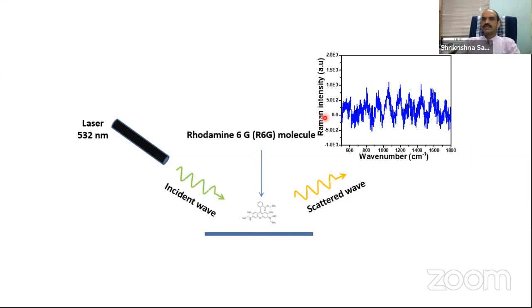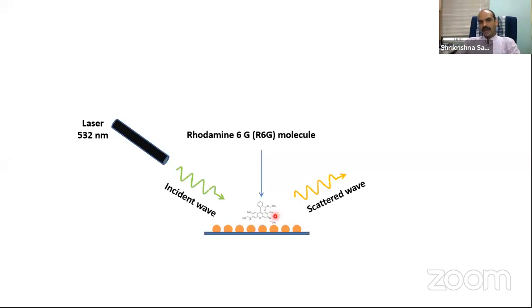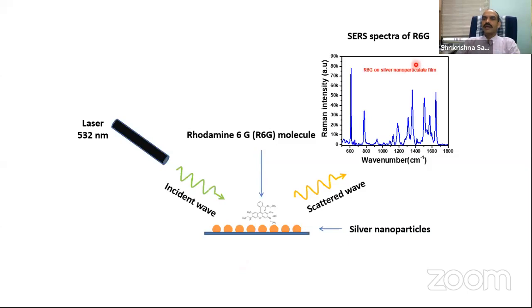This is the intensity. You can see that this intensity is about 0. This is simply a noisy spectrum. However, when I put silver nanoparticles and adsorb this rhodamine 6G molecule on them, and take the Raman spectrum again, you can see that initially the intensity was 0, now it becomes 80,000. So from nothing to everything, that's what we can get. The same molecule, the concentration of the molecule was the same. Now if you adsorb on the silver nanoparticles, you can get 80,000, otherwise you will get only 0.